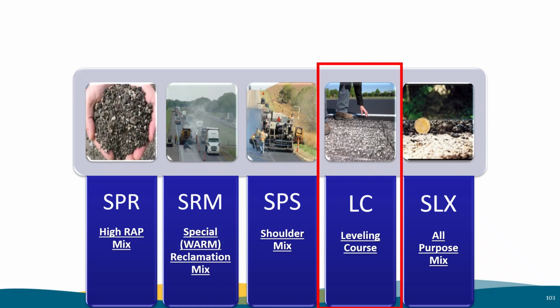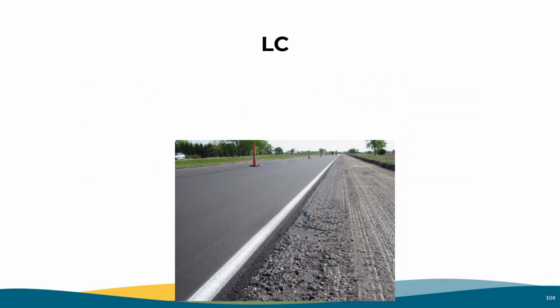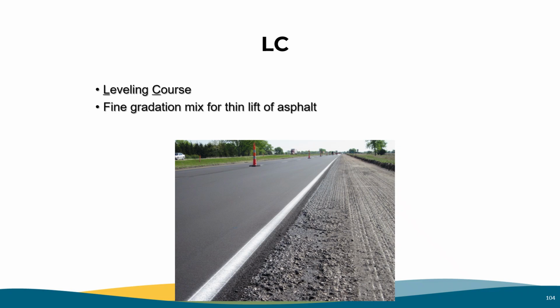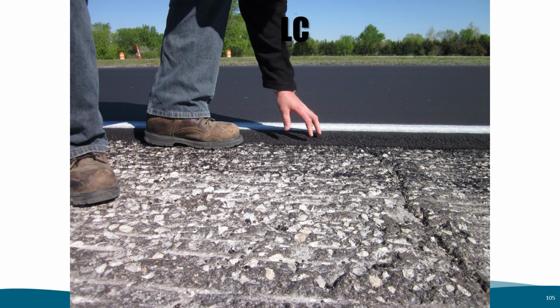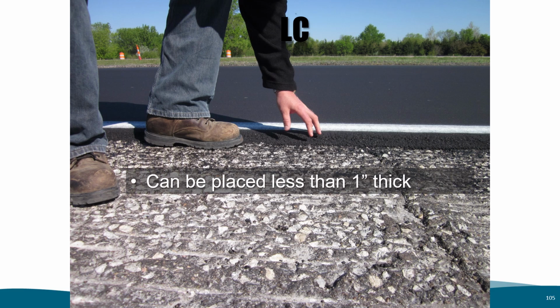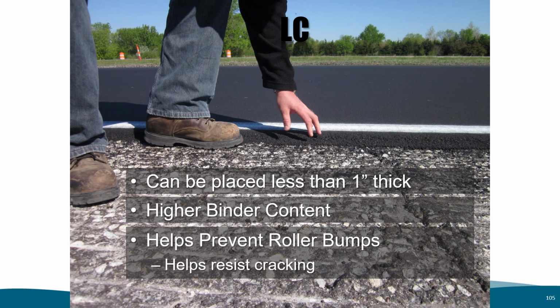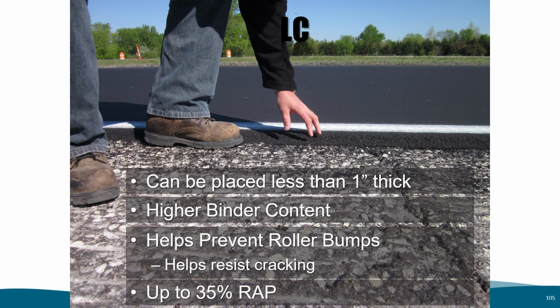Now let's look at the type LC mix, which stands for leveling course. LC or leveling course mix has extremely fine gradation mix for very thin lifts of asphalt. LC can be placed less than 1 inch thick as a leveling course or scratch course. It has a higher binder content, helps prevent roller bumps, helps resist cracking, and this mix can use up to 35% RAP.